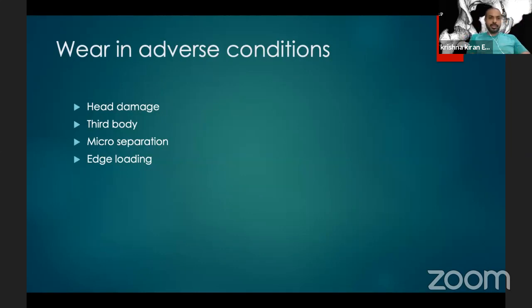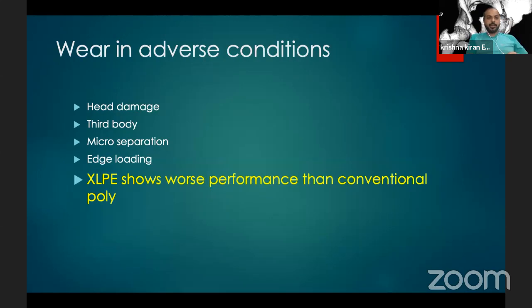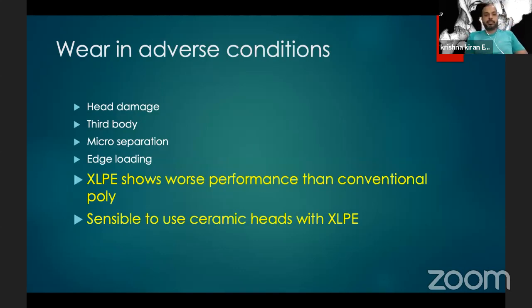The last thing which we must consider is wear in adverse conditions. We must look at how the bearing performs if the head is damaged, if you have third body, or if there is micro separation and edge loading, which is a constant feature inside the body. And here the XLPE shows worse performance than conventional poly. I would recommend that it is sensible to use ceramic heads whenever we are using XLPE, because as we have seen, the head damage and the micro asperities are higher for cobalt chrome heads. However, there is no data in the literature which says that XLPE on cobalt chrome is inferior to ceramic with XLPE.